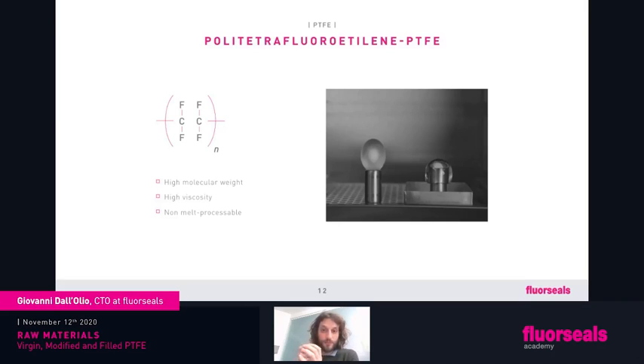PFA, that was a sphere before reaching temperature, once it melts, it's really melting. So it starts behaving like a very high viscosity liquid. So the sphere loses its shape and starts melting. This is why PFA is a melt-processable polymer, can be extruded by screw extrusion or injection molding. PTFE is not.